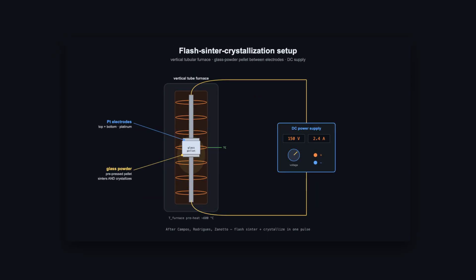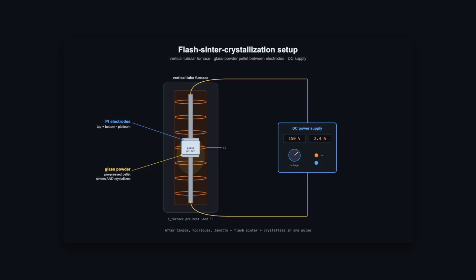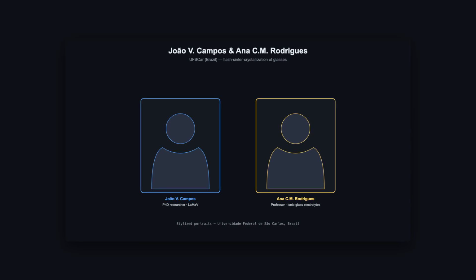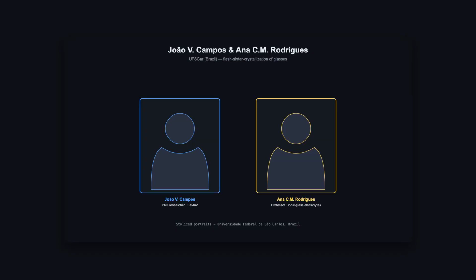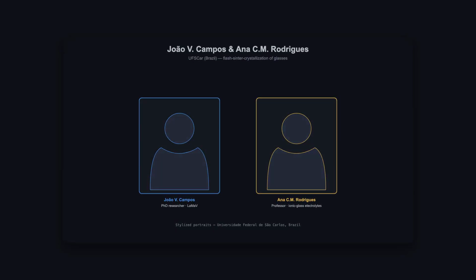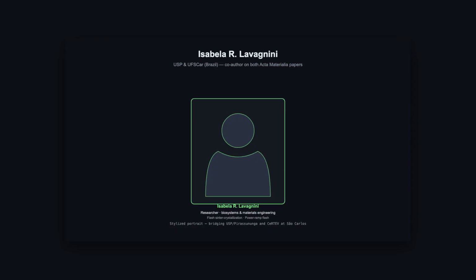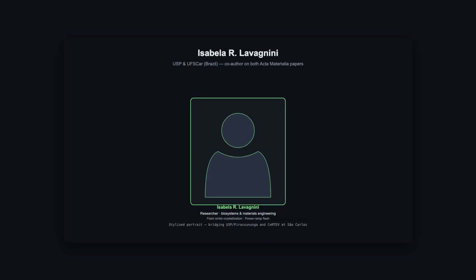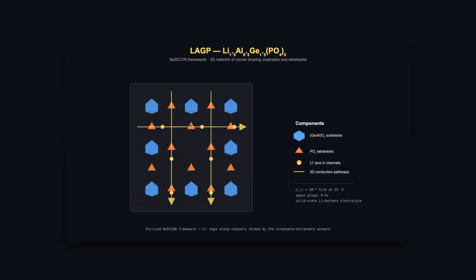And the gate is wider than oxides. In 2022, a group at São Carlos, Brazil, pulled a glass into a glass ceramic in seconds. João V. Campos and Ana C. M. Rodrigues at the Federal University of São Carlos. And Isabela Lavagnini, co-author on both papers, the through line between USP's Pirassununga campus and CERTEV at São Carlos. Working with Isabela Lavagnini at USP and the CERTEV Center, the Center for Research, Technology, and Education of Vitreous Materials. Their material was LAGP, a lithium aluminum germanium phosphate, a NASICON glass ceramic, a solid-state lithium-ion conductor.